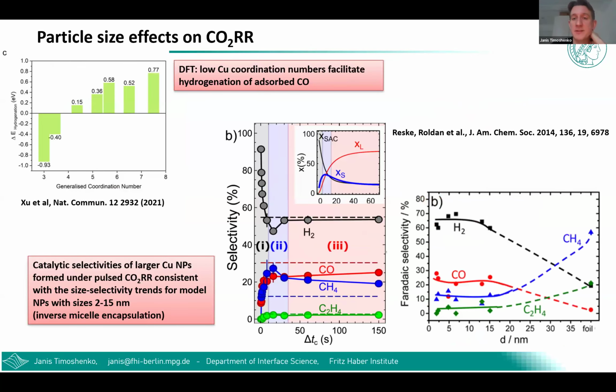And again, it's very interesting that these behaviors seem to be universal across very different systems. We can also find publications where other researchers stabilized similar small copper clusters using a different approach, without applying potential pulses, but by changing the composition of their catalyst in the synthesis. They observed very similar trends, a very similar correlation between the production of methane and the presence of very small, low coordinated copper sites in copper dimers and trimers,